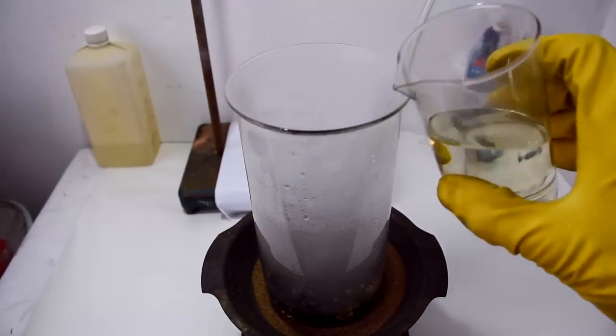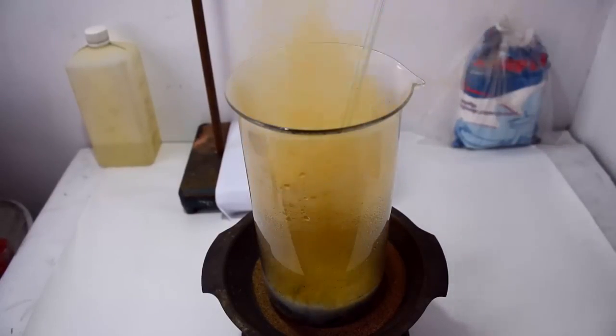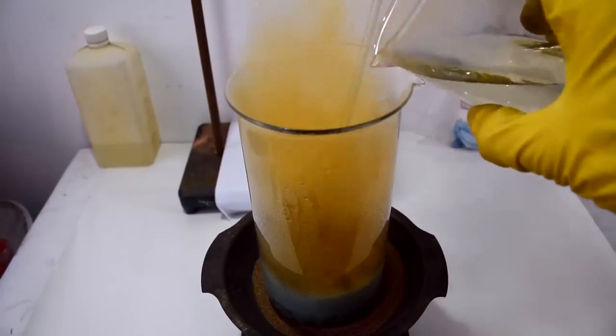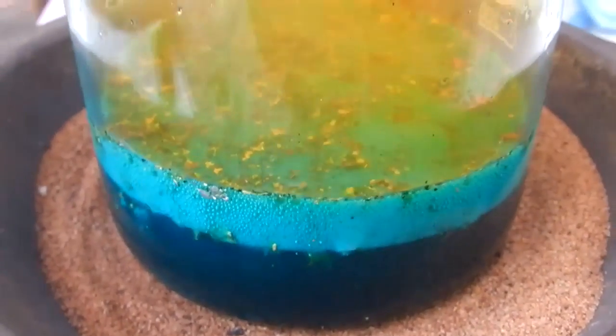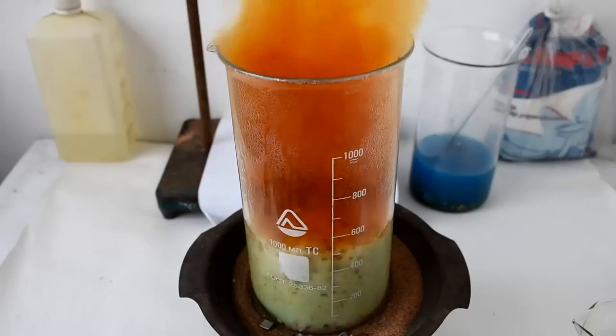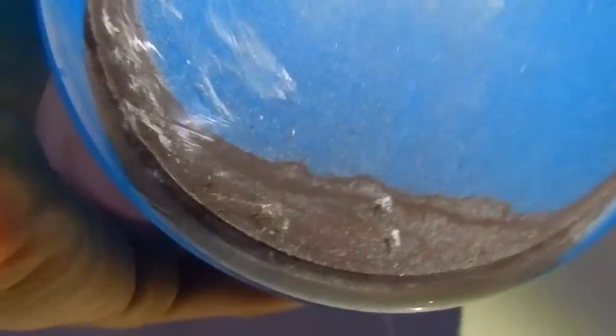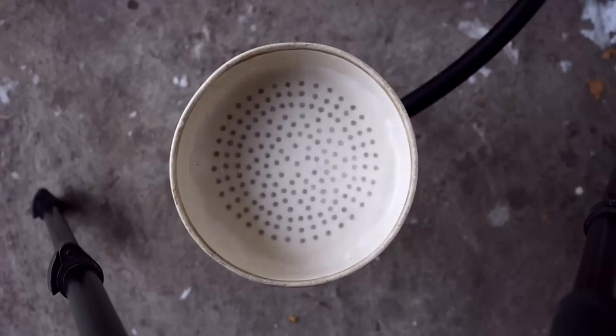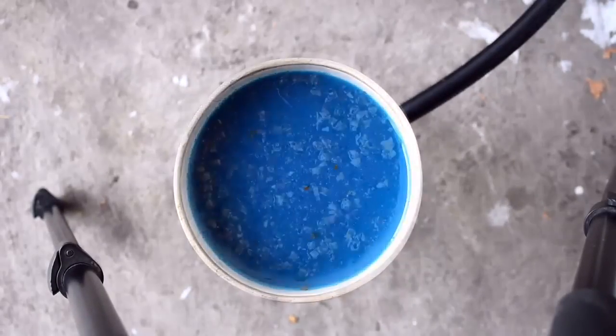The material is covered with water, stands on a sand bath, and we carefully pour in nitric acid. The reaction will be very violent, so we need to work very carefully. Here is an interesting result after etching the connectors with nitric acid. Note that there is already a brown powder in the sediment — most likely during firing the gilding passed into the base and fell out when dissolved. We will immediately run everything through a filter. I prepared 25ml of aqua regia; now we need to transfer all the gold into solution.